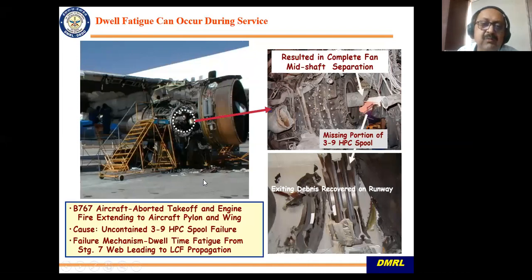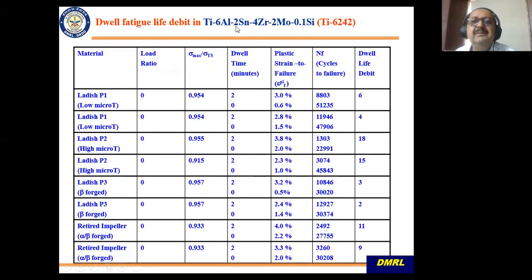And there have been quite a few engine failures. That is why people have started bothering about dwell fatigue also. Here again, I'm showing the processing of 6242, which was processed differently. This is again from Jim Williams' book. You can see that some material was processed to have low microtexture, some material was processed to have high microtexture, and then there are beta forged and other impeller parts also.